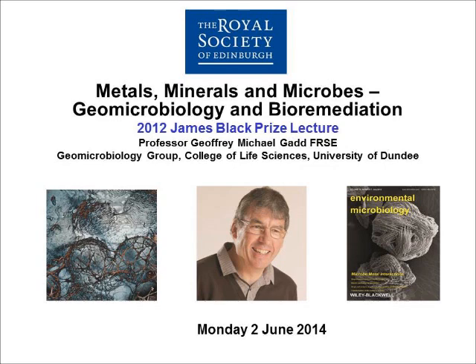And in the silicate, you can see there's a variety of zinc ores, and there's the zinc sulfide, which is the other thing that might be used for zinc. It's got sphalerite. Zinc sulfide is the main ore. And we're interested, because there's a lot of problems there, as we'll see, some leaching and changes. Fungi can change these recalcitrant materials and solubilize them, but reprecipitate as some insoluble minerals, zinc oxalate, calcium oxalate, and also calcite from the calcium that is also present in those minerals. What they can also do is bioleach the zinc sulfide. And this is called chemoorganotrophic leaching to reflect the metabolism, because organic acids are the main